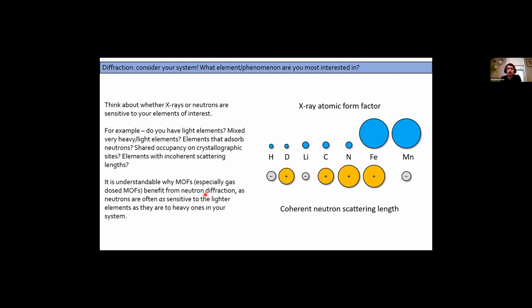But the reason why we're talking about neutrons specifically for framework materials, right, is they're often as sensitive to the lighter elements as they are to the heavy ones. And in a metal organic framework or any of these porous materials, you're probably gonna have a mixture of both, right? There's also added contrast in the coherent neutron scattering length, where you might have negative and positive. So if you have a mixed metal node on your MOF, you're going to be able to distinguish them as well with the neutrons.